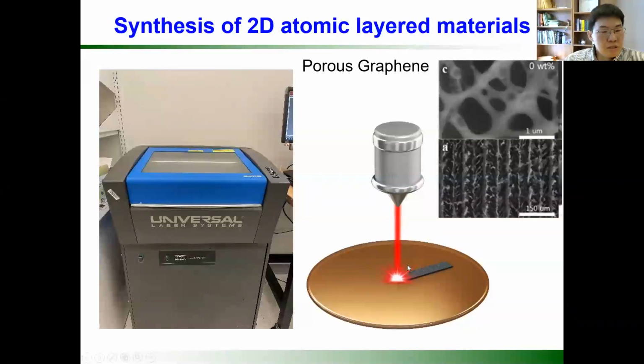We use a polymer to synthesize the materials, as opposed to the metal catalytic films that we use to synthesize graphene with CVD techniques. We use the polymer as a precursor, a polymer that contains carbon atoms. What happens when we irradiate with the laser is that the elements other than carbon evaporate, but the carbon atoms form hexagonally bonded atoms with pore structures. This is how it looks when we shine the light on the polymer materials. In a very short time scale, the carbon atoms form hexagonally bonded structures with pores, and these show graphene-like structures.